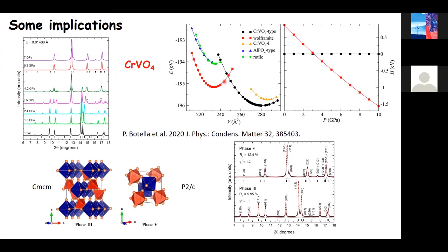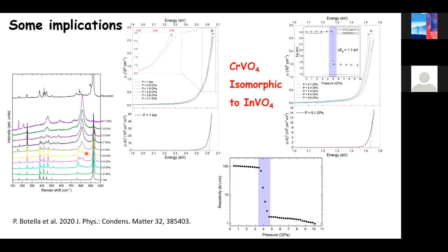And you have here results from calculations supporting the same transition. If you take a look at the enthalpy, the transition is predicted at 3 GPa, and we have seen the onset of the transition at 3.5 GPa. Again, we have done Raman experiments. The Raman experiment showed the same phase transition, and we have also done optical absorption experiments as in the indium vanadate, and we have observed exactly the same behavior.